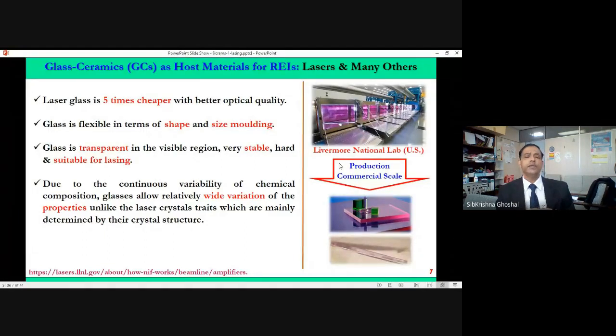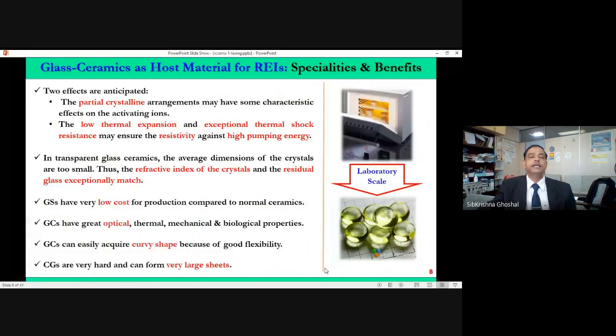So glass ceramic, we can give any kind of shape, molding, and they are transparent. Transparent means maximum light will come out of the material. When the emitter is sitting inside the material, they are stable, they are suitable for lasing. So these are some of the very interesting reasons. That's why Livermore National Laboratory, American Defense, they are producing this kind of phosphate telluride glass at large scale for almost all the defense and other display devices in the technology.